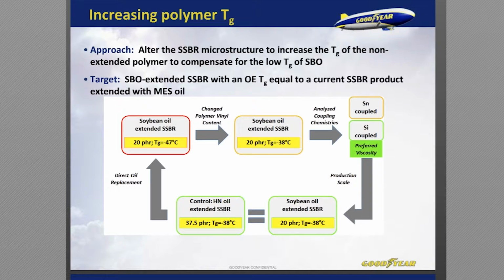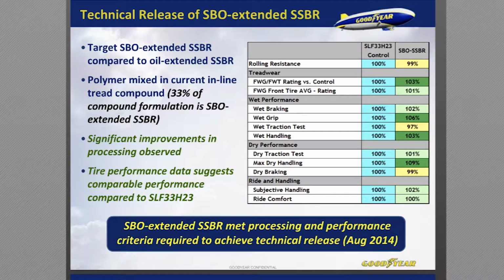So, starting here at the bottom right, you see our control polymer. A direct oil replacement really shifts the TG, and then we did some polymer development work around it to get the same composite TG, only extended with soybean oil. So what does that do? It basically allowed us to combine a high TG polymer that would be good for possibly a wet application, but given the extremely low TG of soybean oil, we are able to balance our properties a little bit better and make a unique material. In August of 2014, we achieved technical release of this material, showing equivalent performance to the inline, but with noticeable improvements in processing, due to the better miscibility of soybean oil with the rubber.